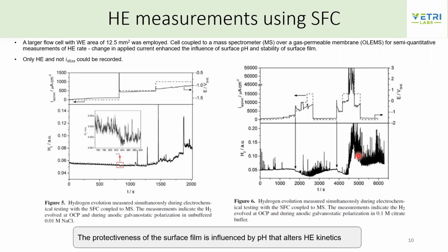With this, they concluded that the protectiveness of the surface film is entirely dependent on the surface pH conditions, and that alters the hydrogen evolution kinetics.